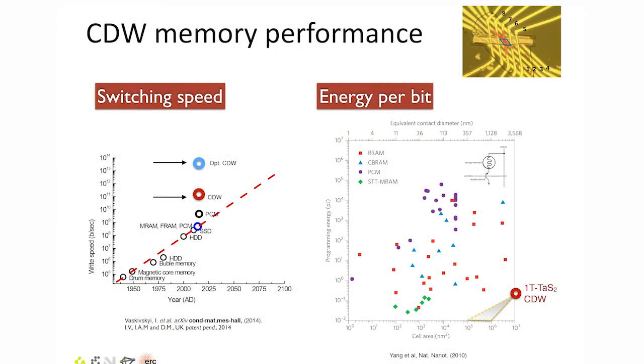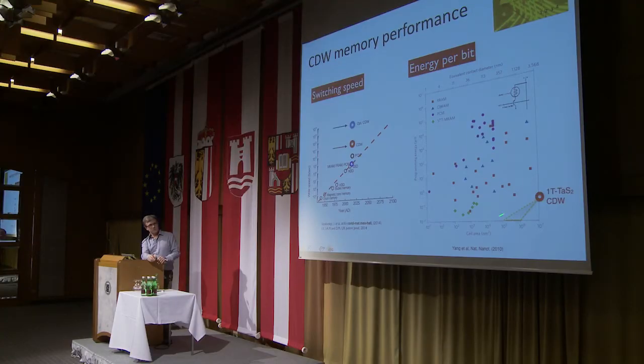And the beauty of this is because the whole thing is totally electronic. There's no lattice rearrangement, recrystallization, or ion motion in this process. It's all totally electronic. The energy required to switch is tiny. So essentially, we are here at the moment. This is our current device size. And of course, the lower the better. And this is the theoretical region where we expect to be with smaller device sizes. So, I think here's an appropriate slide to end with.